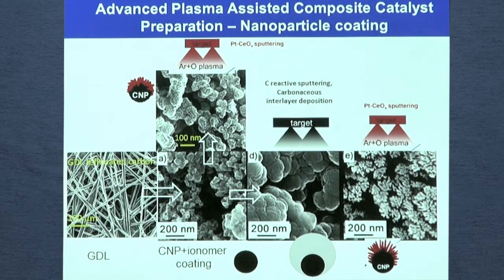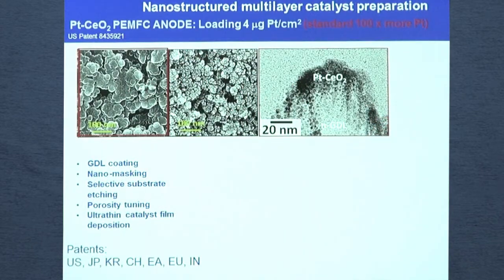And because, as I have shown before, we can increase the efficiency of the etching process by adding nitrogen-doped carbon, we can also first coat the carbon nanoparticles with this interlayer, then etch and deposit the catalyst after. You can see that the porosity is even higher, exactly as in the case of the flat model which I have shown before. So we can tune the porosity, and we have something which is really nicely porous.